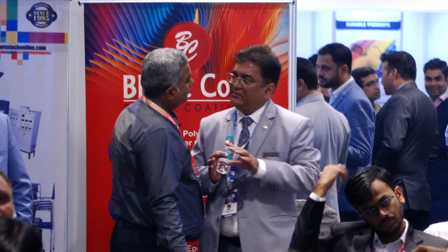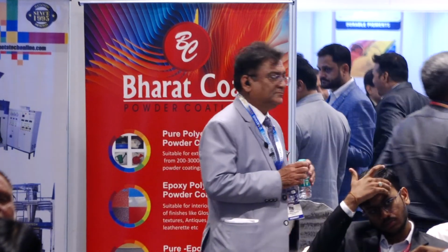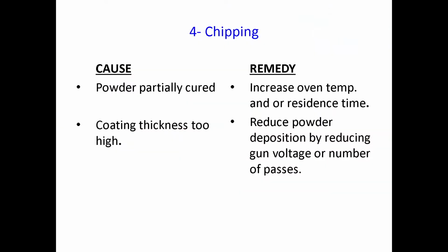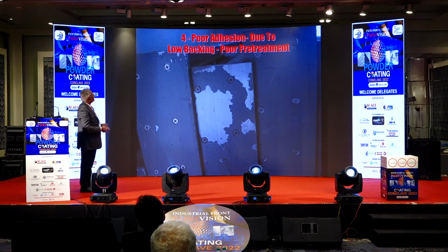Why does this happen? So chipping: the powder is partially cured and chips. If coating thickness is too high, it will also chip. Then poor adhesion; I have shown a panel here.